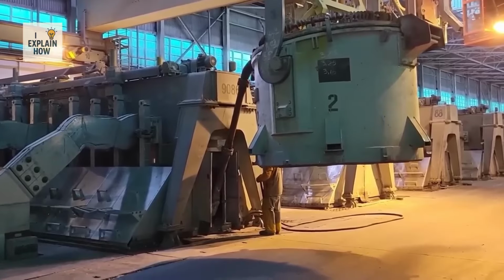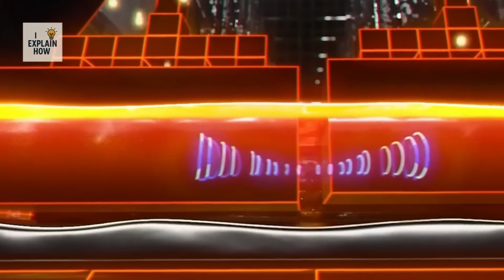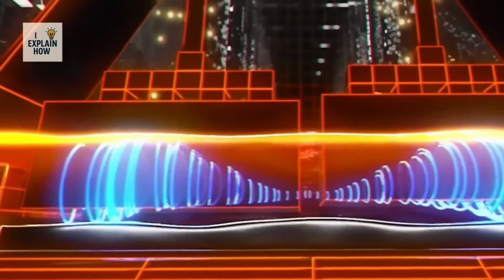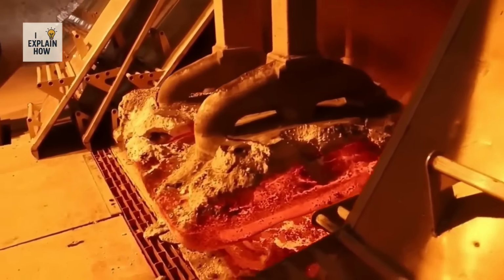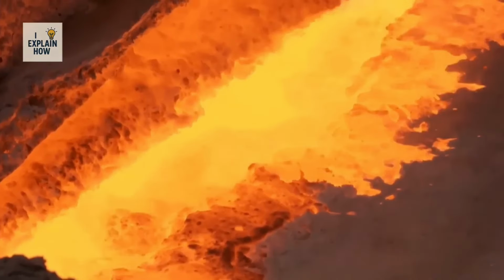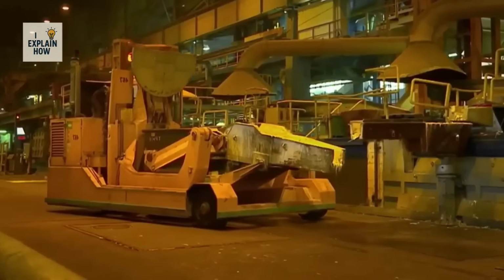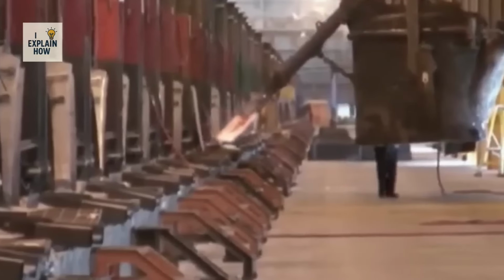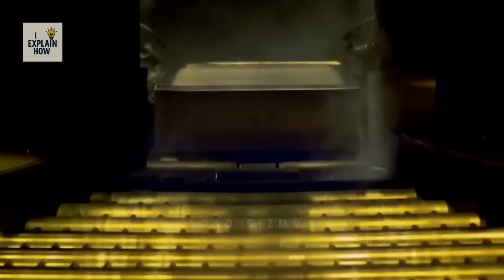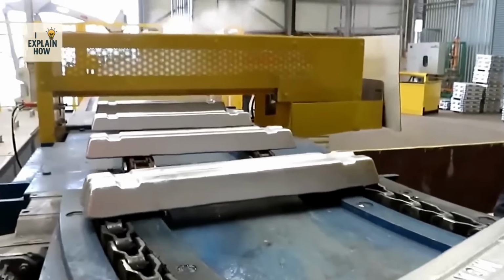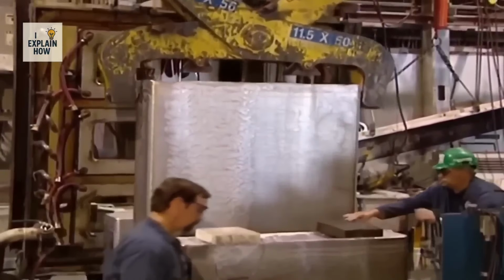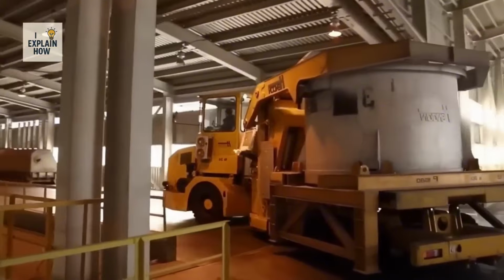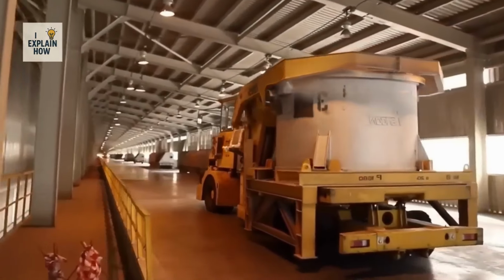In the electrolytic cells, a low-voltage, high-intensity electric current is applied through carbon anodes and a cathode, thus triggering electrolysis. Electricity flows through copper rods connected to the cells. The aluminum oxide molecules they contain are composed of 2 aluminum atoms and 3 oxygen atoms. The electric current breaks these bonds, separating the atoms. The oxygen rises to the surface of the container and reacts with the carbon anodes to form carbon dioxide, while the denser aluminum sinks to the bottom. After electrolysis, the molten aluminum at about 950 degrees Celsius is separated from the cryolite by suction pumping. This process takes place in continuous cycles every 36 hours to extract the metal from the cells.